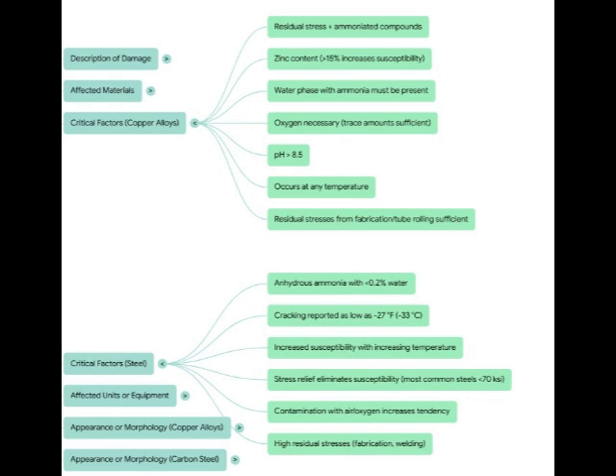And stress, again, is a major player. For steel tanks, steel piping, the focus is often on those high residual stresses left over from welding and fabrication. The sources also confirm that oxygen contamination, even just a little bit of air getting in, makes things much worse. It increases the cracking tendency. Similar to copper, actually, but the way it works chemically is a bit different in the anhydrous environment. What about temperature? Big storage tanks see big temperature swings. Does it need to be warm?